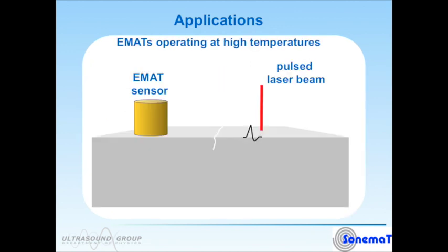Another technique that one often uses with EMATs is to combine it with other forms of ultrasonic transducer. In this example, a pulse laser beam might be used to generate a surface wave. That surface wave could travel to a crack. Different frequencies of the surface wave travel to different depths. So not only will the crack reduce the amplitude of the signal, but it will also act like a frequency filter, allowing lower frequencies to pass under more easily.